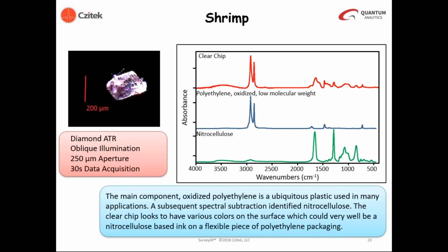This is a particle that was collected from shrimp, also using the digestion sample preparation method. In this case, we were able to analyze the material by diamond ATR using a 250 micrometer aperture and 30-second data acquisition. The primary component of the sample, once again, was polyethylene, but you're seeing some absorption bands in addition to polyethylene. So this is a mixture.